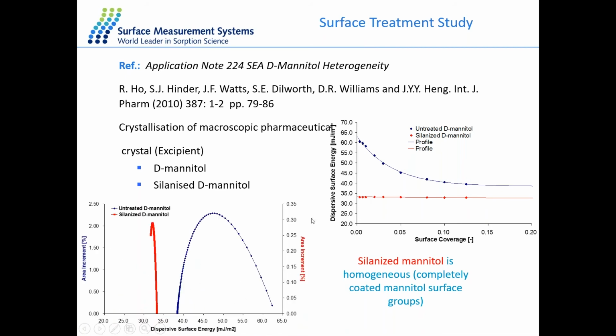Another way that we can understand the sample is by taking a point-by-point integration and plotting that. As a result, we obtain a dispersive surface energy distribution. So we're looking at the minimum, the maximum, and the gamma D50. What we can interpret from this plot is that the wider the peak width, the more heterogeneous the sample, and the narrower the peak width, the more homogeneous the sample. So you can see that silanization has changed the material from something very heterogeneous to something very homogeneous.